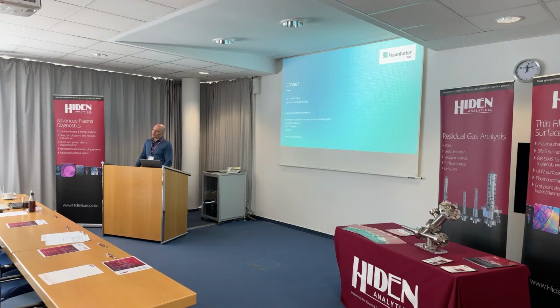What we see, we have our orifice. We use a small one, at least I assume 50 micrometers. If it's small or not, this is something you know better. And we have to grind this all the time because we get thick coating on the nozzle and the orifice, even at short measuring times. We're only measuring for 2 to 3 hours or so between cleaning. The experience is that you have a plasma exposure time for the orifice of like 2 to 3 hours. And you see that the signal is going down, so you have to do some initial measurement, then do your real measurements, and then repeat the one you did in the beginning and see if you still have the same transmission through the orifice to the device.